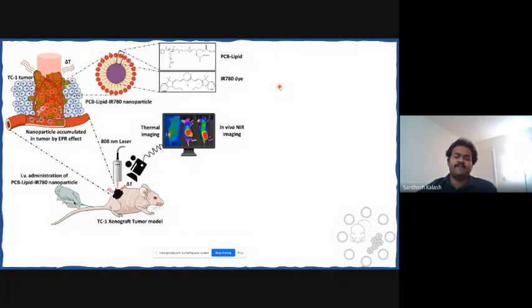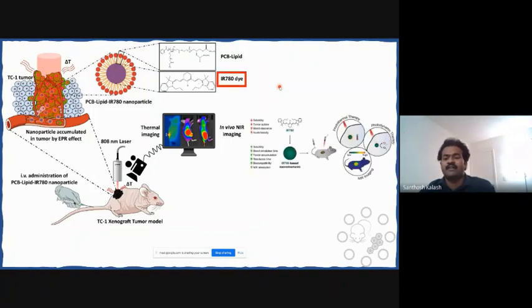The second component in this material is the dye, IR780. This dye is used for phototherapy, and this particular dye is a heptamethine dye. It is highly hydrophobic, having very poor solubility in water, and also very poor uptake in the tumors. It gets cleared very fast in the blood, and also has potential toxicity. That's the reason why we use this dye incorporated in the nanoparticles.